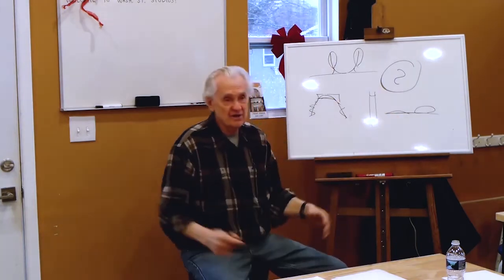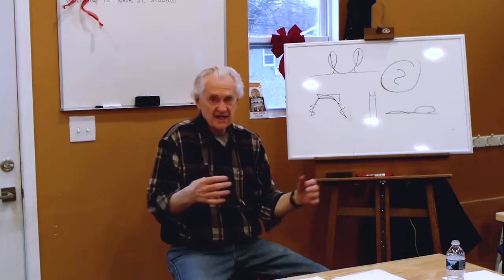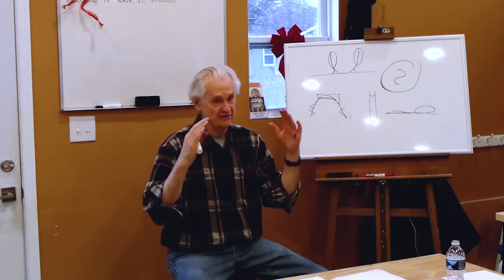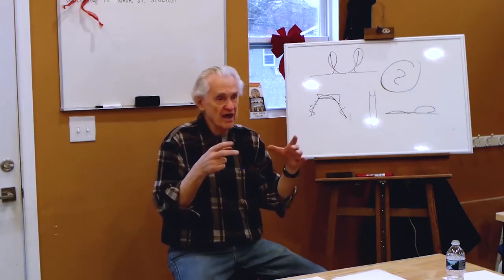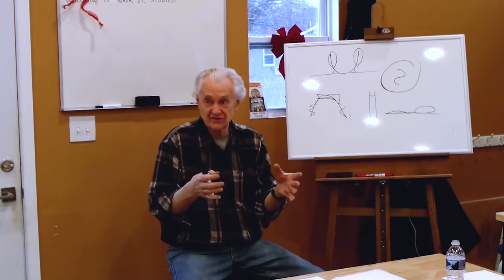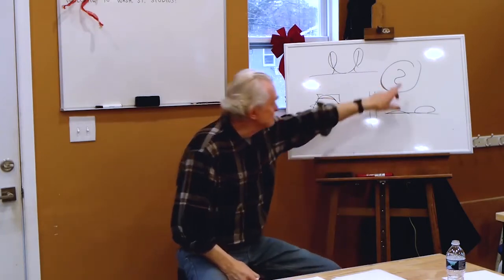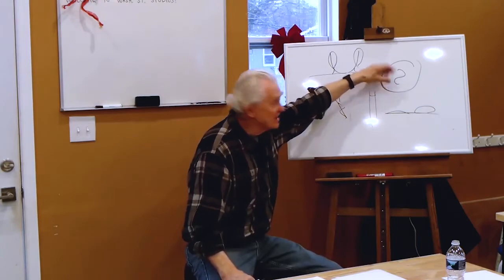That's what happens here. The bottom tears because the bottom part that they've trimmed wants to pull in, but in order to pull in, it would have to pull the sides in with it. It can't, because the sides have already gotten a little stiffer. So at some point, if the bottom is thin and the sides are stiff, all the bottom can do is tear. It's not going to stop shrinking when it dries. It's going to shrink, but if it can't pull the sides in with it, all it can do is tear away from the sides. Usually it stays attached to the sides and tears in the middle.